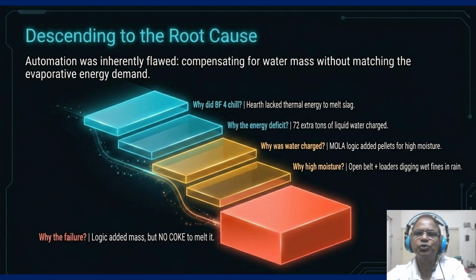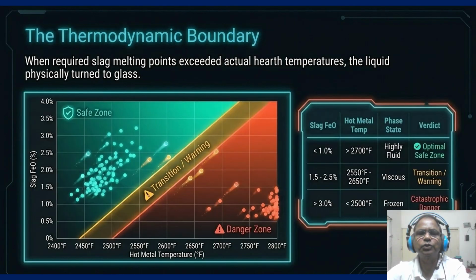So, this energy deficit pushed us across a critical thermodynamic boundary where liquids physically turn to glass. So, the thermodynamic boundary. This heat map is our no-fly zone. The y-axis is slag iron oxide and the x-axis is hot metal temperature. The emerald green safe zone requires temperature over 2700 degrees and FeO under 1%. Look at those orange and red clusters in the danger zone. When our temperature dropped below 2500 degrees and FeO spiked over 3%, the slag phase state shifted from highly fluid to frozen.